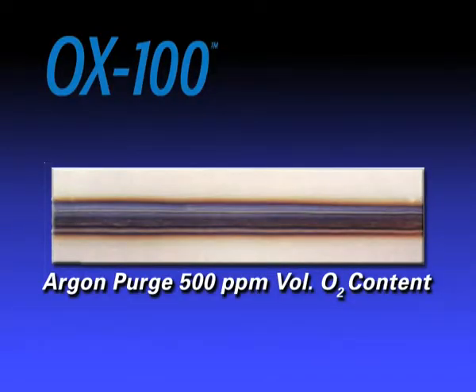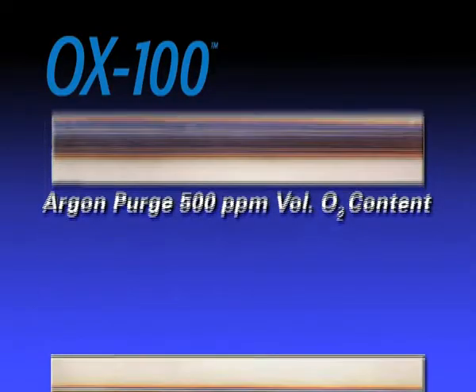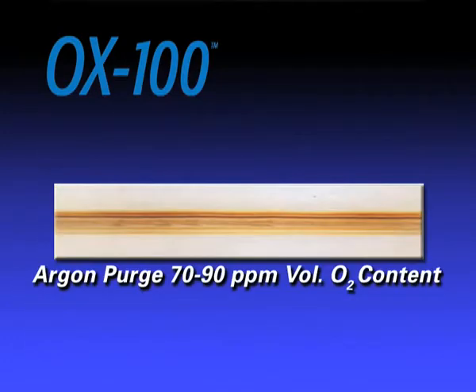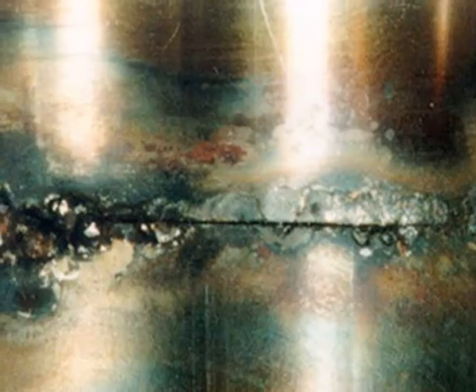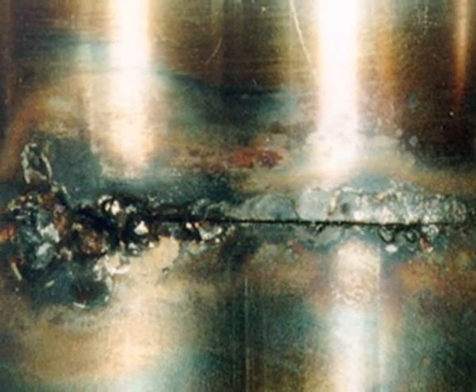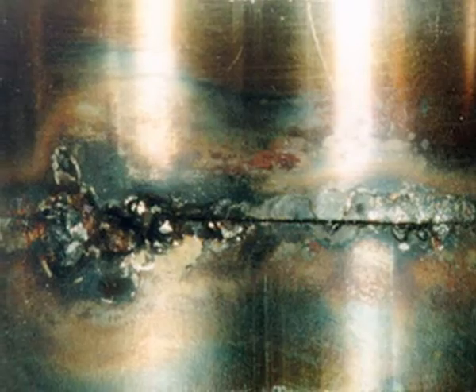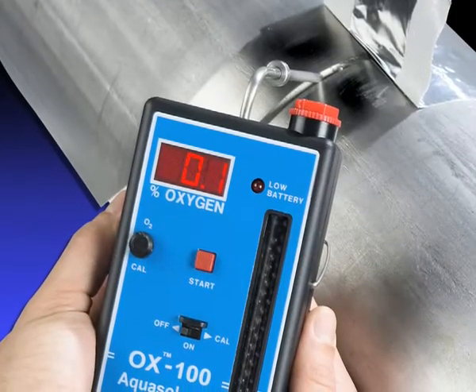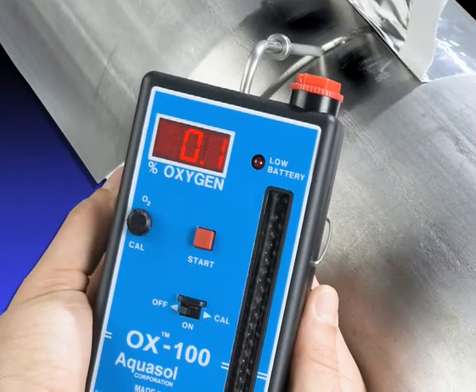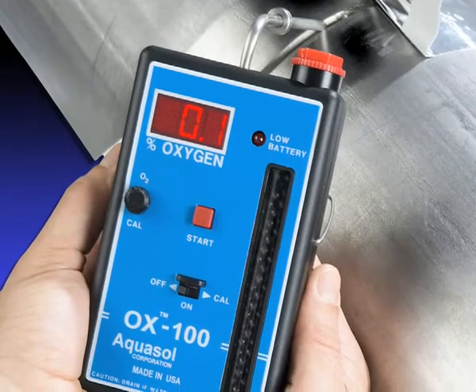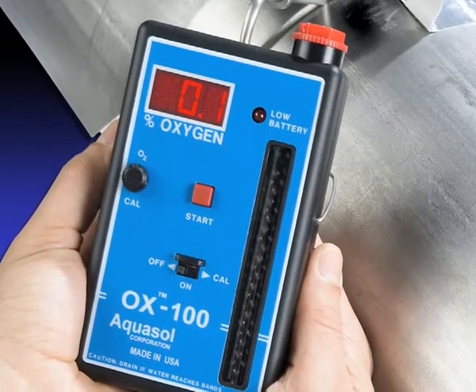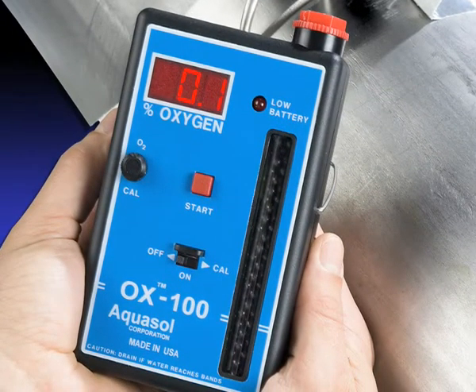The heat tint color varies from black to blue, violet, and straw color. The chromium content of the metal just below the oxide is reduced, resulting in greater risk of corrosion and failure. To prevent this from occurring, welders should monitor oxygen levels during the purging process until they are certain that the required level of oxygen has been achieved.